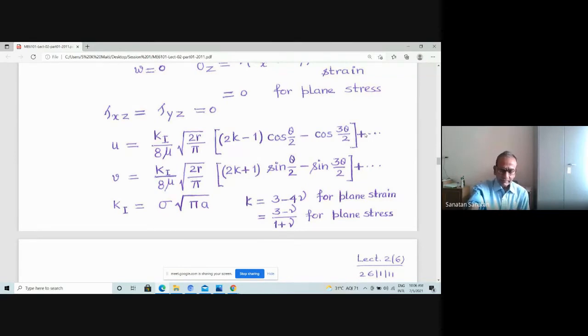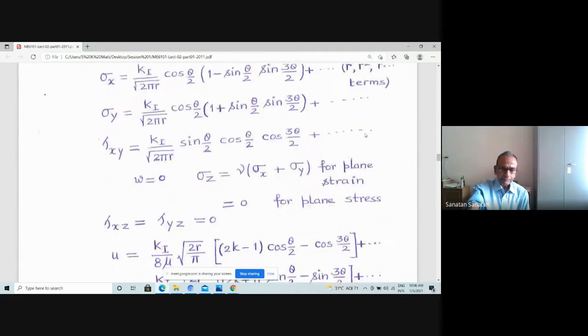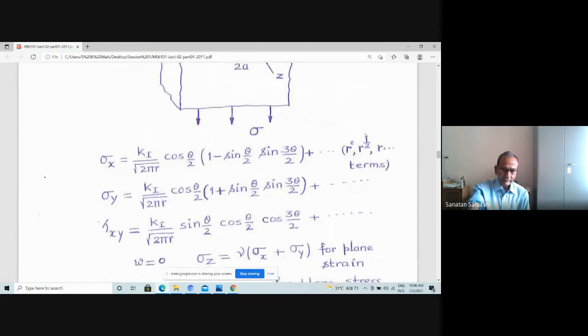So therefore, please have a study of the form of the stress field. It is K1 by root 2 pi r. K1 is a parameter which is related to the crack size and the external load applied, and r is there as inversely proportional. It is proportional to 1 by root r. So as r reduces, stresses increase.